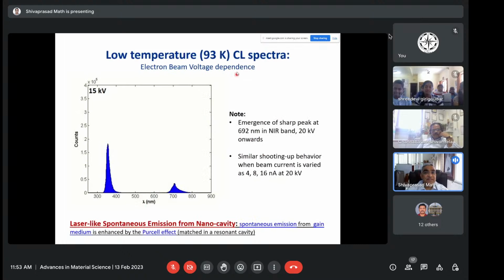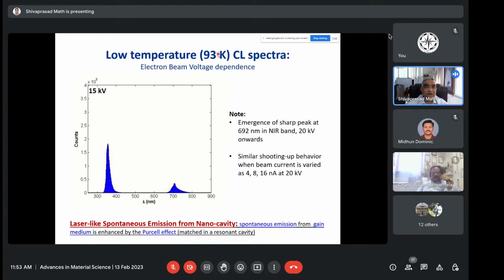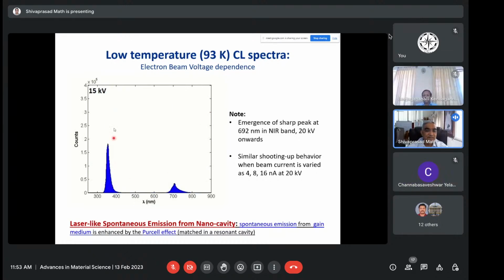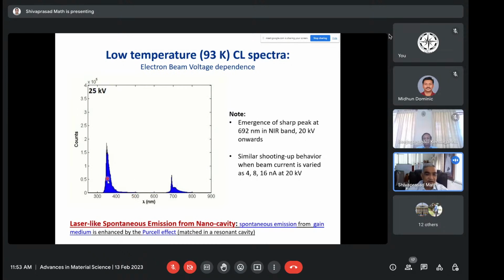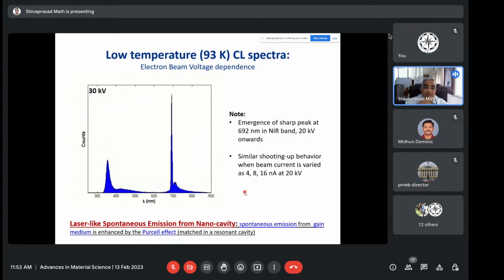So now we did the same studies at low temperature, at liquid nitrogen temperature. Very difficult experiment, the cathodoluminescence at low temperature, but it gave us a very interesting result. You see, the conversion, of course, is taking place from this bandgap emission to the infrared emission. But you see here, now the peak is much sharper. Like a laser-like emission. We are still not confident of calling it a laser emission, but we call it laser-like spontaneous emission, because it's not a stimulated emission like in a laser, right? So it is a spontaneous emission. So whether it's a laser or not, we don't know.